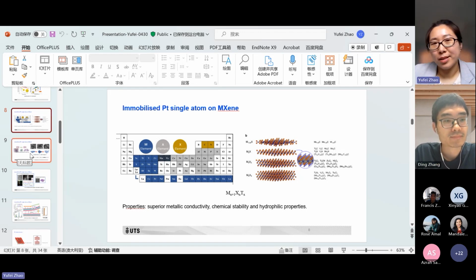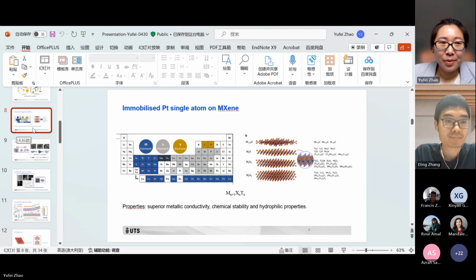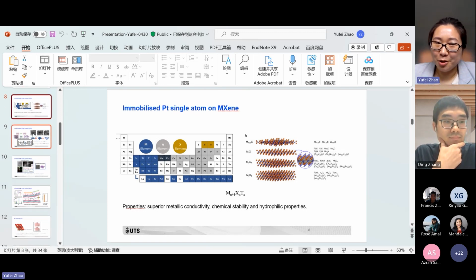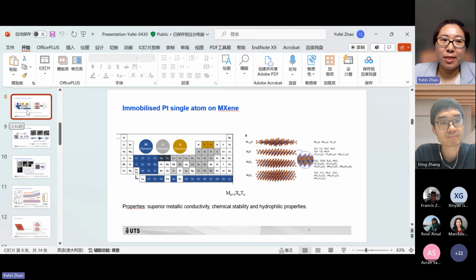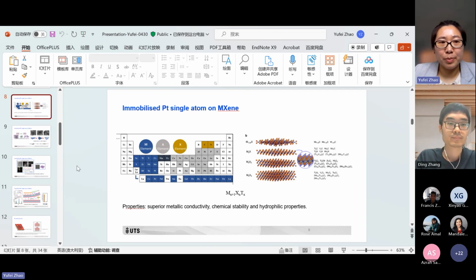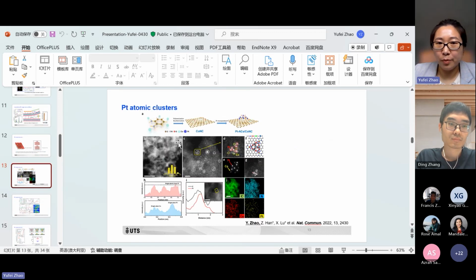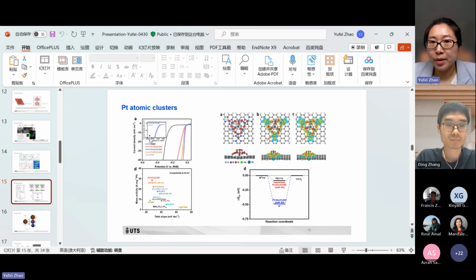If we work on the HER side, and if we want to reduce the cost for industry, we definitely want to reduce the usage of platinum. So in that way, I think single atoms and atomic clusters should be better. The usage for single atoms or atomic clusters, normally for the Pt deposited on the substrate, is around 1%, or we can even make it lower, like for the atomic clusters, we make it 0.5%, and still it can show very high performance.